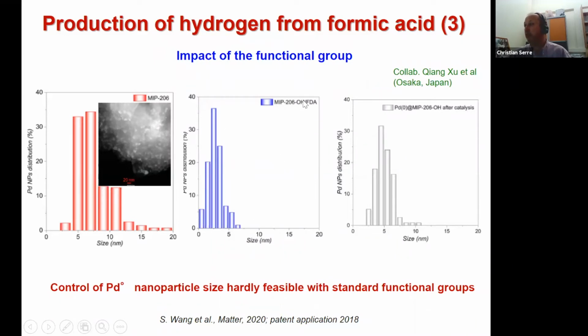If you use an OH functionalized group here, then the particle size distribution is narrower, and it focuses around 2 to 3 nanometers. So it means that part of the nanoparticles could be inside the pores and the rest outside. What is nice also is that after the catalytic reaction, after the reduction of formic acid into hydrogen, you see that there's almost no change in the particle size distribution. So it means that there's little sintering occurring during the catalytic reaction. But let's say the first conclusion here is that with the traditional standard functional group, it is hard to control the particle size distribution of palladium inside the pores of the MOF.